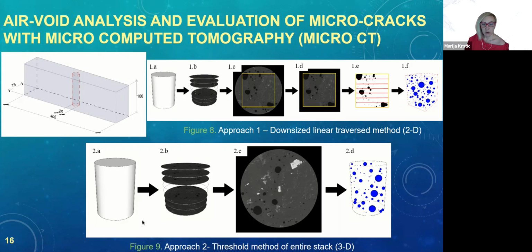We used 2 different approaches for determining air void content. One of the approaches was basically a downscaled linear traverse method from ASTM C457. So we took the cores from the beams and scanned them through micro CT scan, and then we coupled that with ImageJ and did the image processing. This method had images taken every 1 millimeter under the assumption that air voids are not larger than 1 millimeter. And then we just applied a regular linear traverse method, just downscaled. So that was one of the approaches, and we call it the 2D approach.